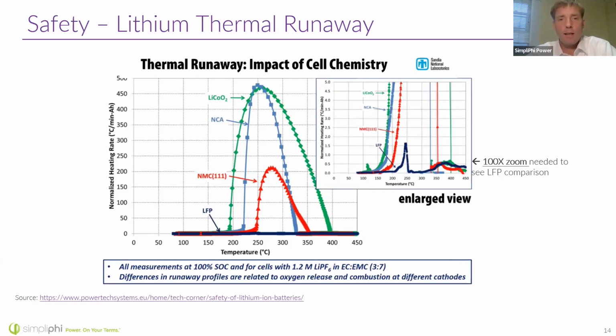So if you have a bigger battery, you're taking into consideration the size of the battery in amp hours. When you look at this, LFP is in the dark blue, and it's right along the horizontal axis here, meaning you can barely even see the heat given off by LFP compared to the other cobalt-based chemistries. If you zoom in on this, there is a peak for the LFP batteries, but it's 100 times smaller, right? It's much, much smaller. You can see that the lithium cobalt oxide batteries are hitting the scale of 450 for normalized heat released, whereas you're only at 1.5 for lithium iron phosphate. So again, just highlighting the safety for you there.